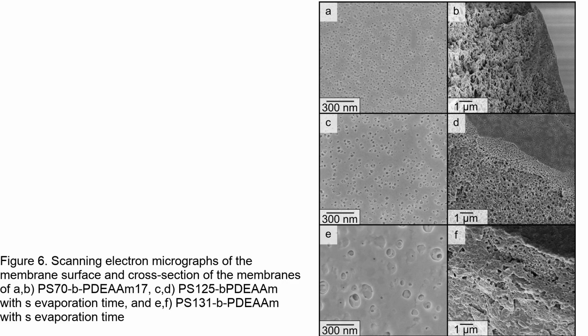These SEM images show the surface and cross-section of the membranes fabricated from the block copolymers. The membrane of PS70-b-PDEAAm17 exhibits a porous structure with a sponge-like substructure. The membrane of PS125-b-PDEAAm43 has a similar structure, but with larger pore size. The membrane of PS131-b-PDEAAm42 shows a relatively dense surface with very large and ill-defined pores.